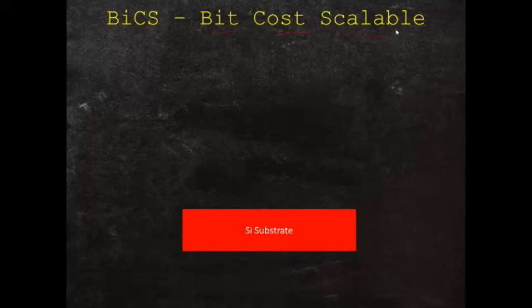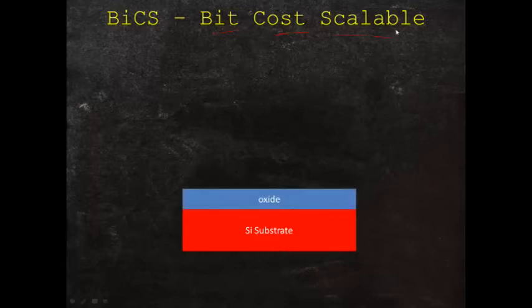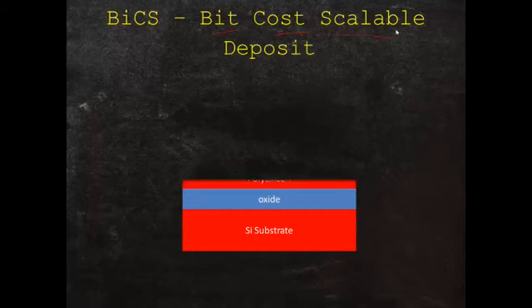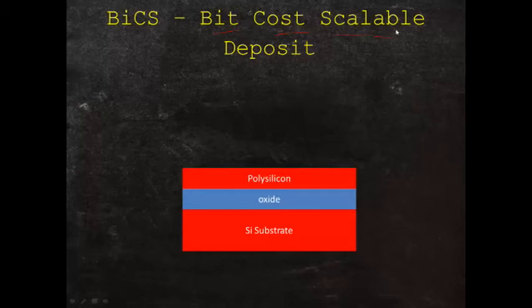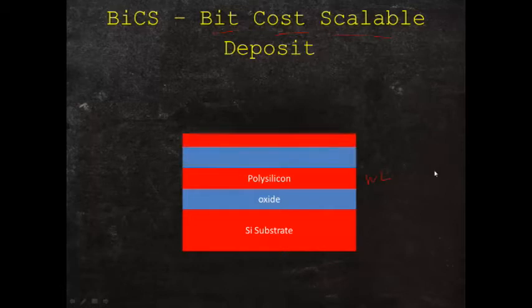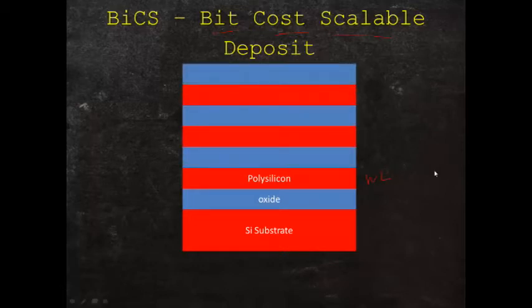This is Toshiba's design, and we start by laying down a CMOS logic layer. On top of that, we'll put silicon dioxide as an insulator, and then a polysilicon layer is grown on top of that. This can be considered to be the first word line of this stack. Then we keep stacking, depositing layers until we decide we have enough.